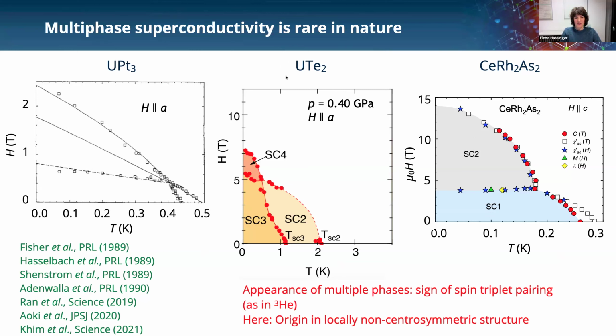In both of these materials, the appearance of multiple superconducting phases has been interpreted as a sign of spin triplet pairing. This followed the ideas of superfluidity in helium-3, where you have three different superfluid states that can be identified with different functions in the spin part of the Cooper pair wave function. In this material, however, cerium-rhodium-2-arsenic-2, we have a different way of understanding the two superconducting states, and it's based on the locally non-centrosymmetric crystal structure, as we believe. So I'm going to tell you how this works.